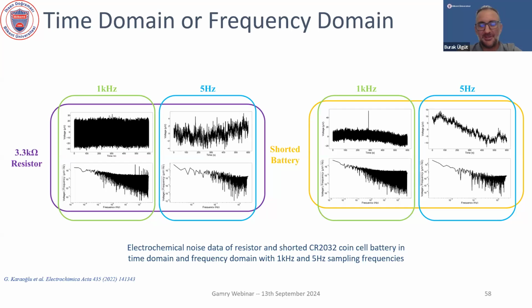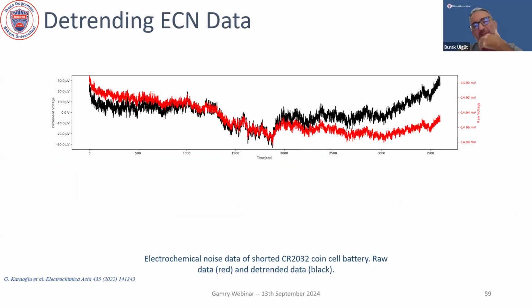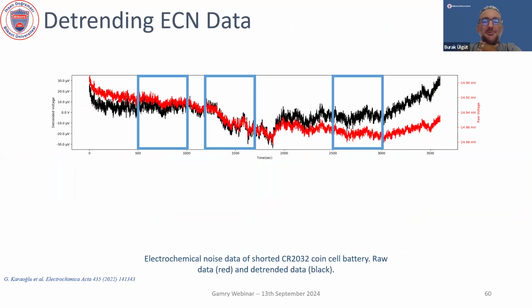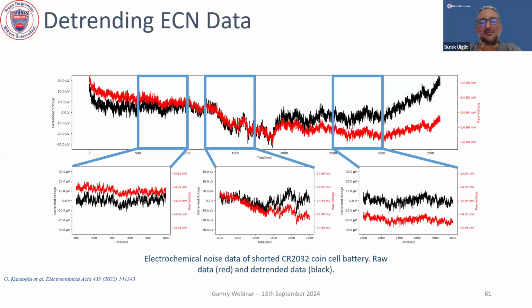Okay, so in order to illustrate this, we took this data that is 1 hour long, and we took 3 separate sections of it, and we started with an action that's deemed benign in the noise community, detrending. So just by detrending it, we can actually do a lot of damage, as you can see. The middle part looks like this is a trend, the red, it is going down. But as you look at the big picture, it's actually not going down. This is just a dip in time.